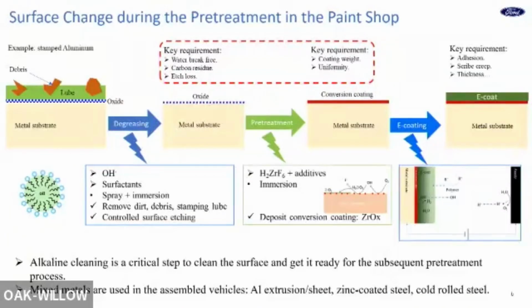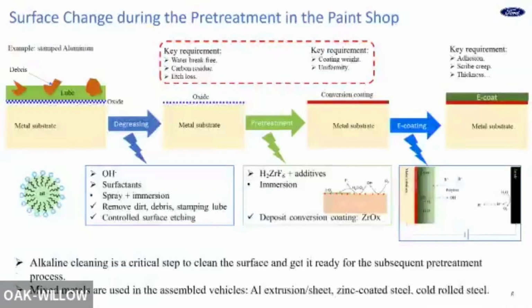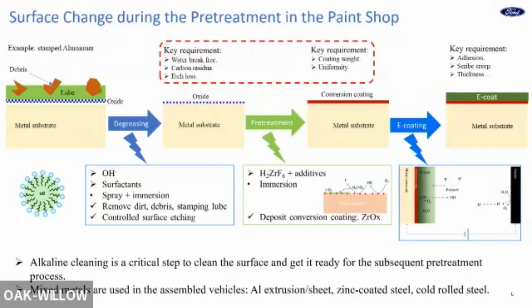So first, the surface treatment process in the paint shop. Here we use an example of stamped aluminum. Normally you have a lubricant on the surface. You also have dirt. You also have some oxide, maybe from the heat treatment or from the rolling process. First, it will be cleaned in the degreasing solution. Normally it has high pH. It can be hydroxide based or based on other chemicals, and also has some additives like surfactant to remove the lubricant from the surface. It can be immersion or spray or both.